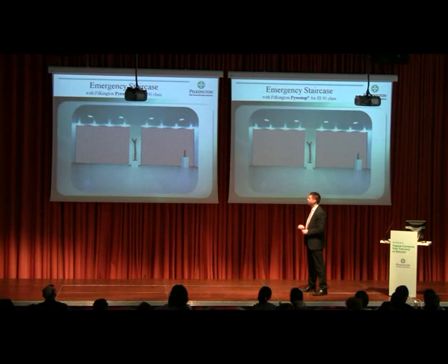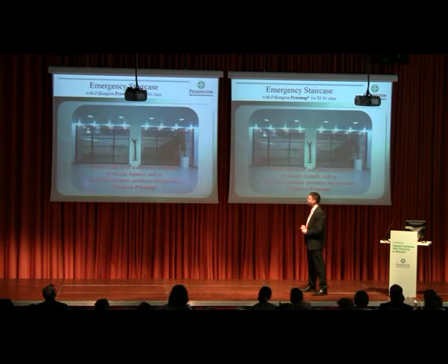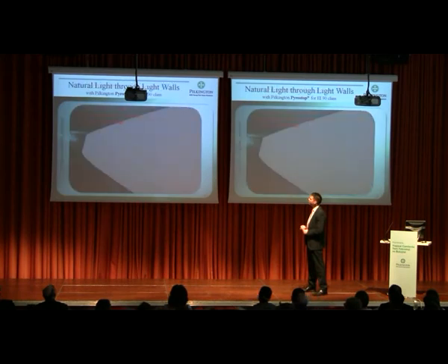Same for an emergency staircase, for example. You won't see it because it's still a brick wall, but if you remove it and put some glazed partition inside, you have such a partition in that case for EI90, so 90 minutes integrity and insulation, to let the people escape over the escape route for a time of 90 minutes. Natural light through light walls.